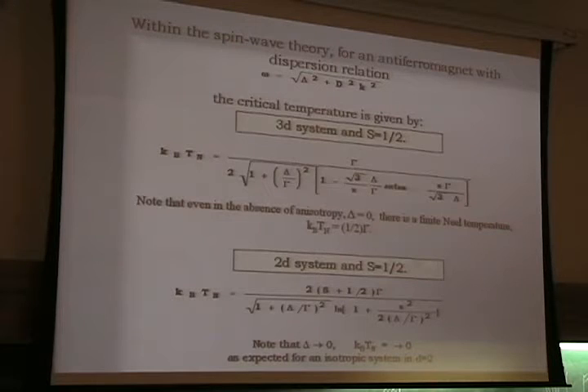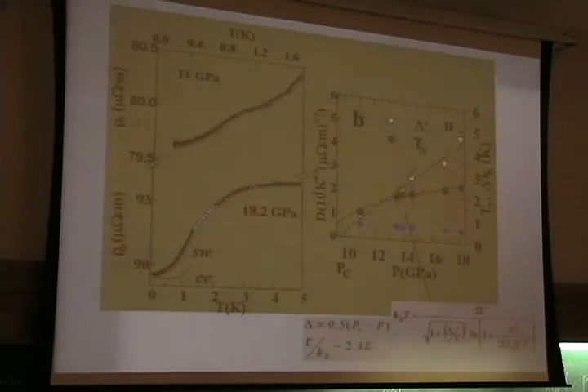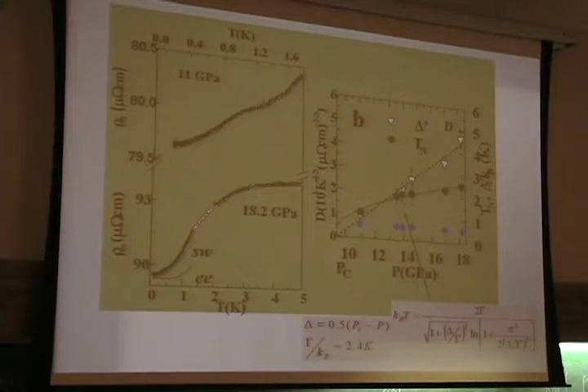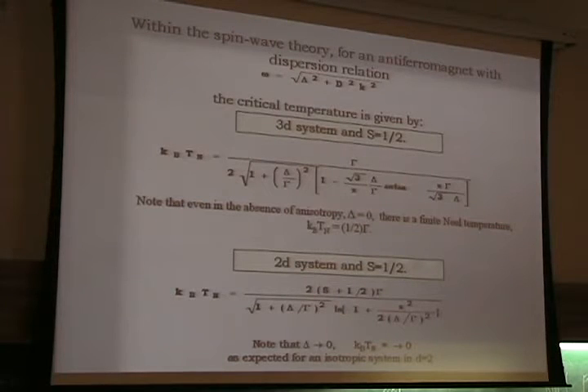Here it's nice to show you that in a 3D system, Tn is given by this formula. And you see, as delta tends to 0, Tn tends to a constant value. But if you go to a 2D system, when delta tends to 0, Tn tends to 0 as well. So, since you have a system where the delta and Tn have the same trend, as Tn goes to 0, delta also goes to 0. And then this is a hint that this system, in an isotropic antiferromagnet, may behave like this, that Tn goes to 0 as delta goes to 0.